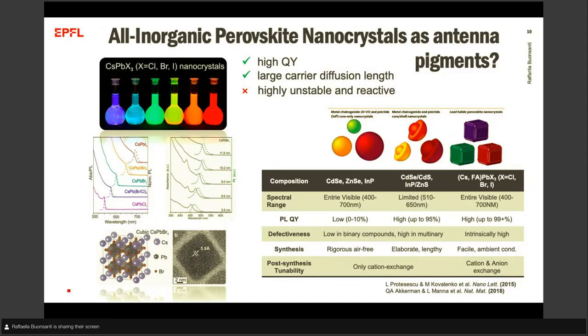And basically, right as I started my laboratory, so at the end of 2015, these perovskite nanocrystals were introduced. They are special because we can change their optical properties, not only with the size, but also with the composition, so by just changing the halide. They have a very high quantum yield compared to many other quantum dots reported in the literature. They have a large carrier diffusion length. They're also quite straightforward to synthesize, but they are highly unstable and reactive. So if we really wanted to use them as the antenna pigments, we had to first solve this issue, to at least measure them.